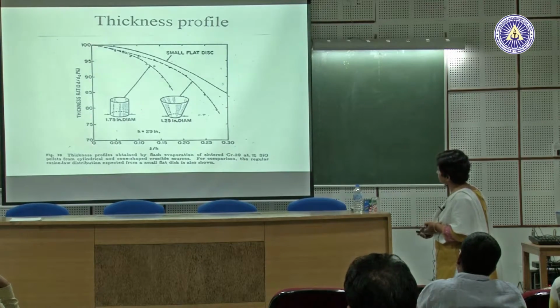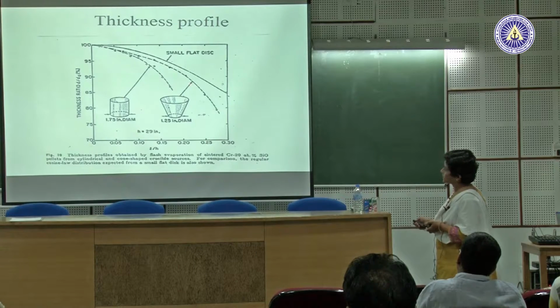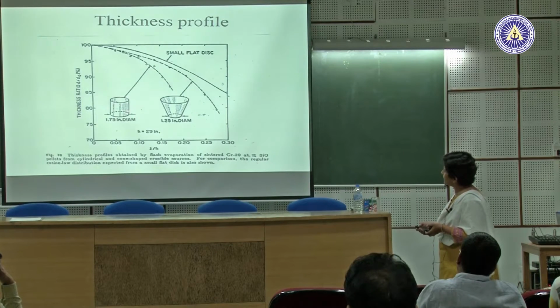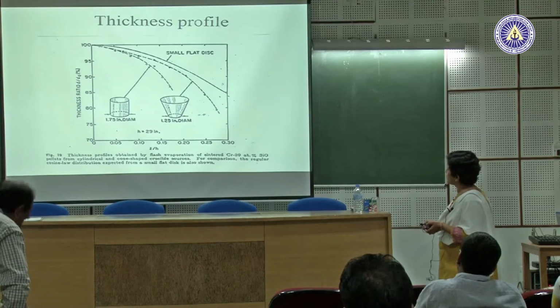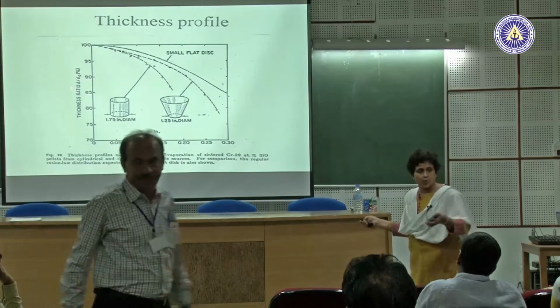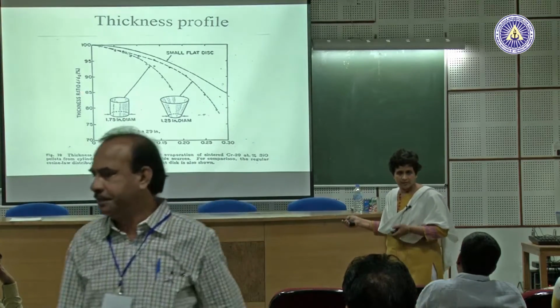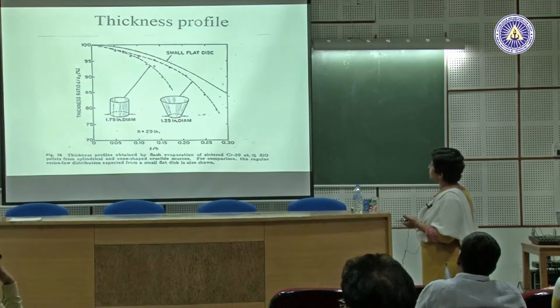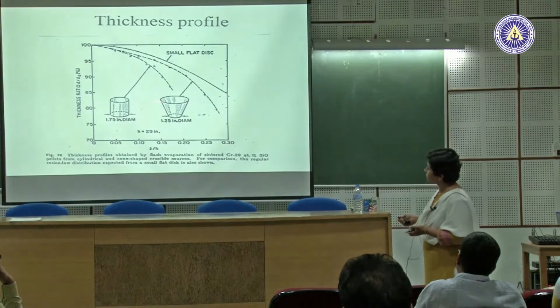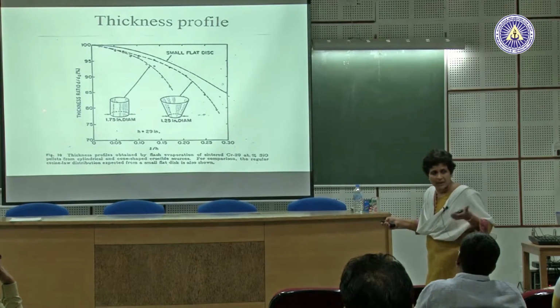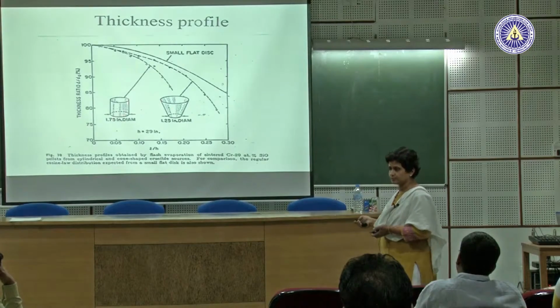You would see that at the center, if it is 100%, as you go away, and you don't have to go away too far, it's only 0.25 of the edge, the thickness starts dropping. And since you keep the material in some container, the container itself, whether it's a cylindrical one or a conical one, will decide how fast the non-uniformity takes place. So there is a lot of work that goes on in deciding how you design your source such that the thickness uniformity is pretty good.